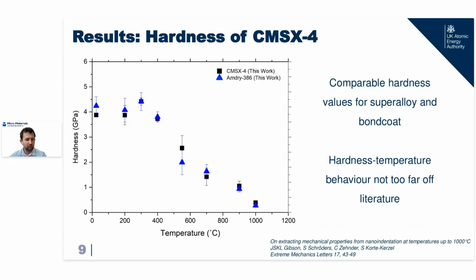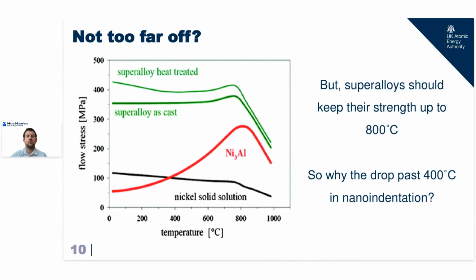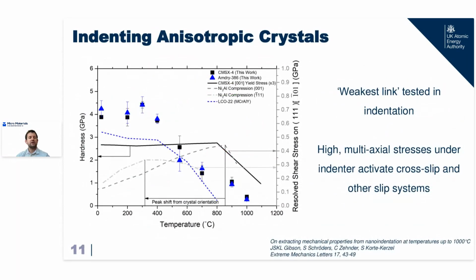Now, those of you who like a superalloy will notice that there is a problem with pretty close, in that whilst we maintain our indentation hardness up to about 400 degrees, a real superalloy should keep its strength up to about 800 degrees. So what's going on? Why is there this 400 degree discrepancy between the small scale and the large scale? Well, it's not a size effect problem for once in our nanoindentation lives. It's actually a crystal orientation problem.